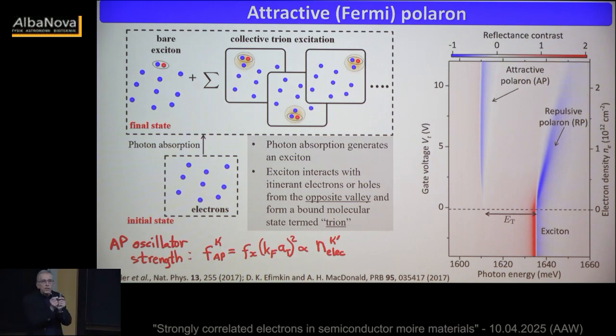So the excitonic weight is distributed in between the two. Now, very important, and this I will show you shortly, is that the oscillator strength of this resonance, if I integrate the area underneath, is directly proportional. This is an exact expression, by the way, within this shaded image. And it's directly proportional to the electron density in the opposite valley. That is, if I look at sigma plus attractive polaron, it's proportional to the density of electrons in the sigma minus valley.